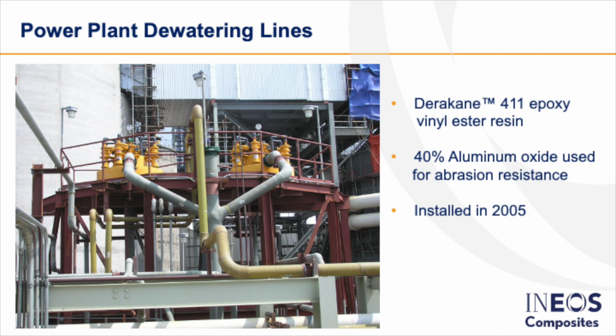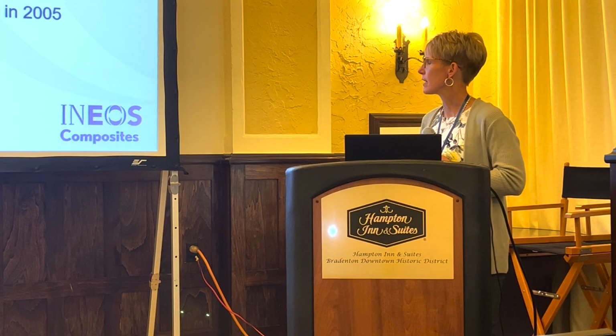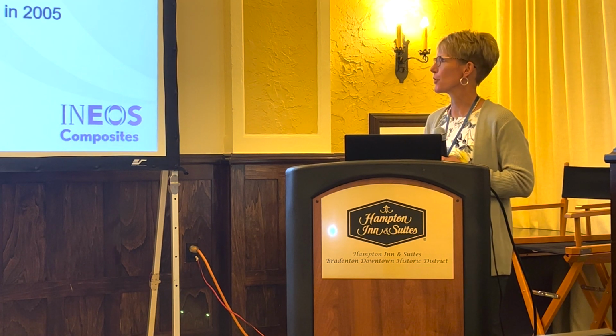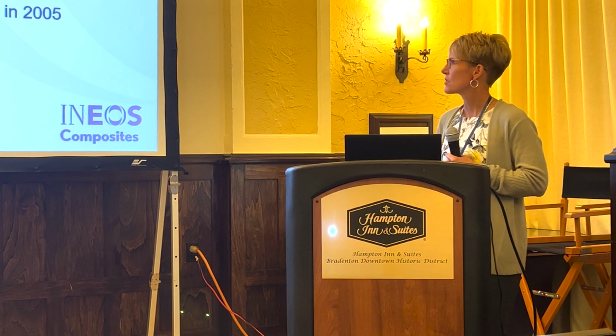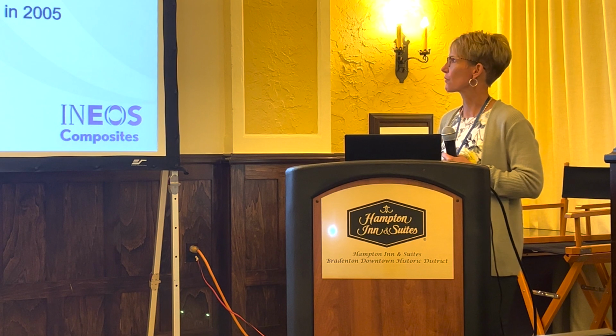This is a picture of some dewatering lines in a power plant. An example of, we talked about yesterday about abrasion resistance. So in this situation, some abrasion resistance was needed, so 40% aluminum oxide was incorporated into that corrosion liner to provide that necessary abrasion resistance in this service. So these were installed in 2005.